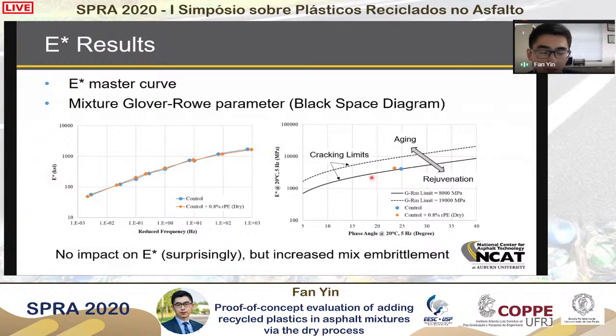So not only do we get an indication of the mixture stiffness, but also we can consider the brittleness of this mix. And in this case, if we look at the location of those two data points, the orange is with the plastics and the blue is the control. As we can see, the one with the plastic has a much lower phase angle when we test it in E-star, which indicates a little bit increased embrittlement. I'm showing the arrows that we typically see with the impact of aging and rejuvenation. So in this case, there was not much increase in the stiffness, but adding plastic definitely makes the mix a little bit more brittle. And that will affect the fatigue resistance when we look at cyclic fatigue data, as I will be showing in the next slides.